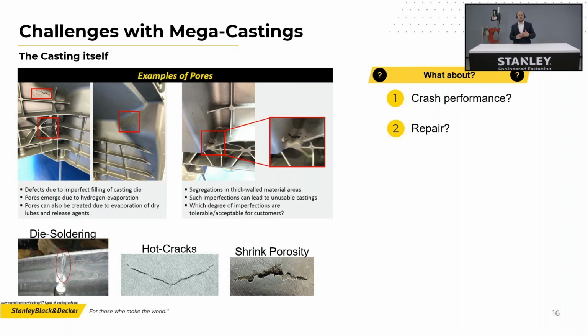First of all, you will have imperfections in the cast, meaning you can have pores, holes, cracks. You can see pictures here on that slide of a hot crack, for example, shrink porosity, die soldering, when the material is gluing against the tool, the press, and then you rip out some of the material. You can have these imperfections. You can have pores up to 3 millimeter or even bigger.